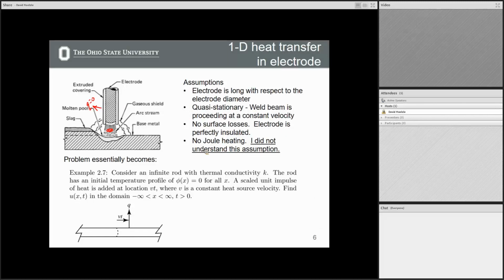Maybe my naive understanding of Joule heating is off, but I didn't understand this assumption one bit. Joule heating is basically heating that comes from current running through an electrical resistance, and to me, this is exactly the definition of Joule heating. The way in which they eliminated Joule heating is that they said this is a solidification temperature here, whatever the solidification temperature of the metal is, and this is the hottest temperature right here. So instead of assuming that there is some sort of heat source, they said that there is just a temperature gradient here, and there's no Joule heating, so that all the heat transfer comes from the fact that you just have two different temperatures. This assumption made no sense to me at all, but these people are dead, so I can't go and argue with them.